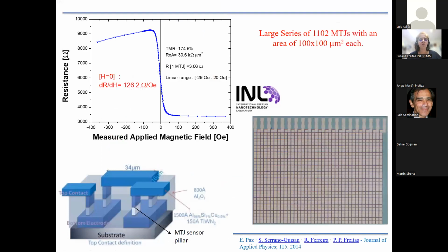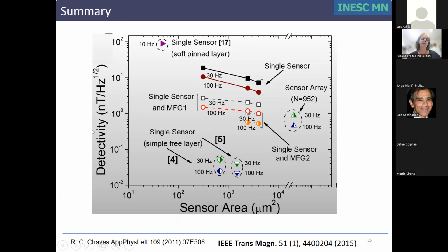Another strategy is, instead of just one pillar with large area, where the magnetic response can be difficult to achieve, it is many times easier to have a sequence of several tunnel junctions connected in series, each one with a smaller area. Each one will have a very well controlled linear range, which is easier to control, and then we add several of them. In this example there are more than 1,000 MTJs, each of these squares being an MTJ or TMR device. If we have more than 1,000, we can still maintain a large output response, and this will favor the noise response at the end. So if we then control the detectivity, the minimum field that we can obtain should be as low as possible.